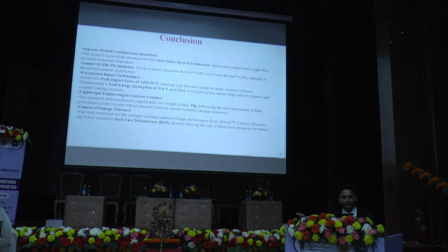Now coming to the conclusion. The superior hybrid configuration was identified using interlayer hybridization. Sample 10, having the Dyneema and Xylon combination laminate, emerged as the optimal material architecture, achieving a peak impact force of 3692 Newton and demonstrating a total energy absorption of 39 Joule. The study confirmed that the strategic stacking sequence of high performance fiber minimizes the back face deformation, as we mentioned through this microCT analysis, directly reducing the risk of blunt force trauma to the wearer. So thank you.